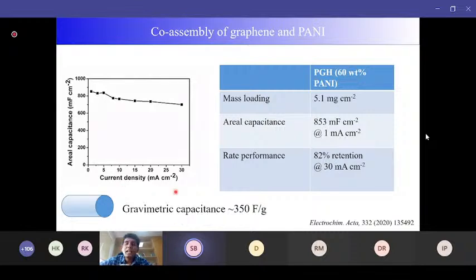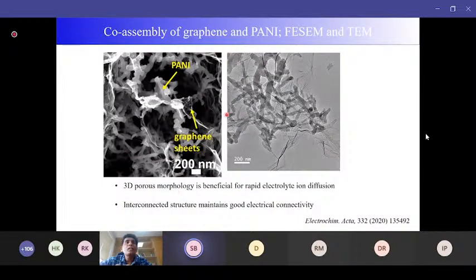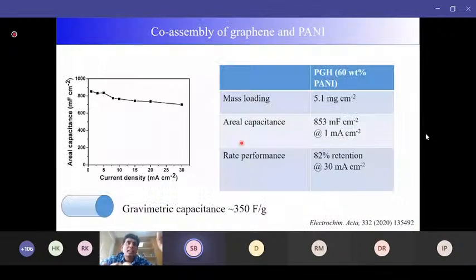So this is one of the ways to increase the gravimetric capacitance. Another is that here the graphene sheets are wrapping the polyaniline. There is no direct atomic level connection between the polyaniline and graphene. This is a kind of physical wrapping. So it is possible that if we can downsize the polyaniline to a nanoscopic scale, and also grow it directly over the graphene surface, there will be a direct connection of the polyaniline with the graphene surface. So how to do that?